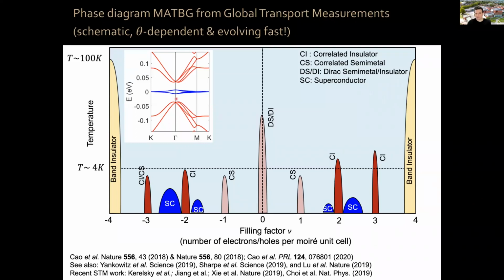Then you hit this single particle band insulator. So this is what you get. A band insulator at 4 holes per Moiré unit cell. If from charge neutrality you fill with electrons, at 4 electrons per Moiré unit cell, you hit again a band insulator. Now in the middle, when you're working in these flat bands, what you have is at each integer, from -3 all the way to 3 electron holes per Moiré unit cell, you have some feature at these integers. The most pronounced are typically the correlated insulator states at nu equals 2 and -2, often also at 3.